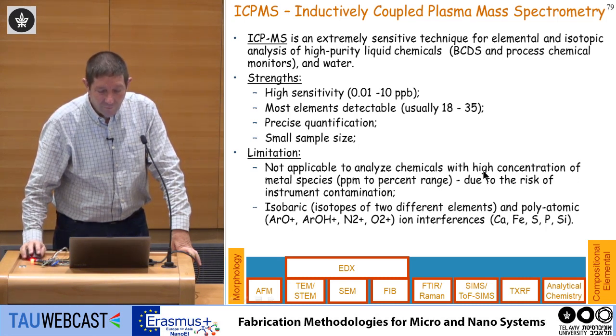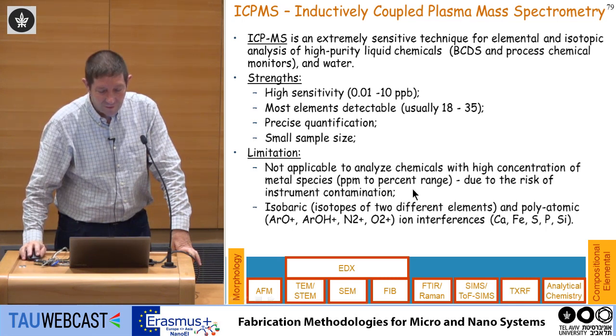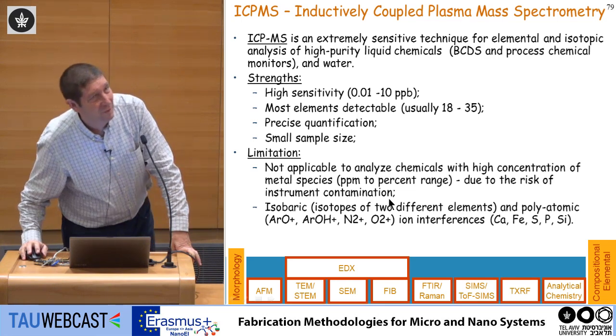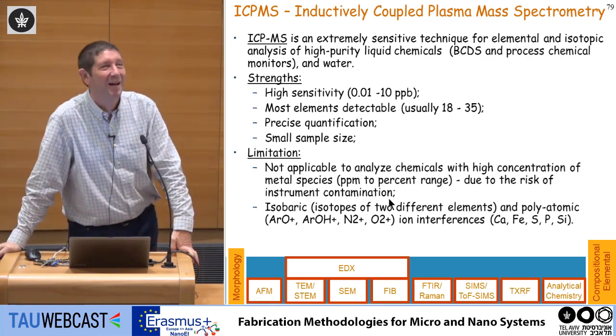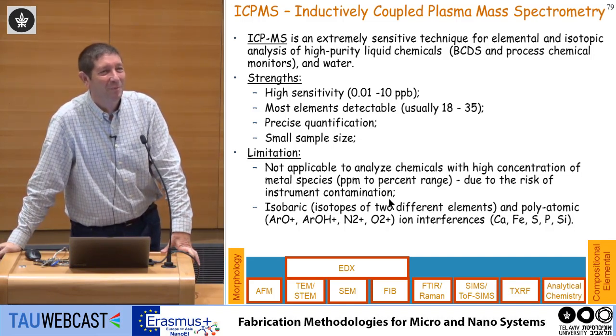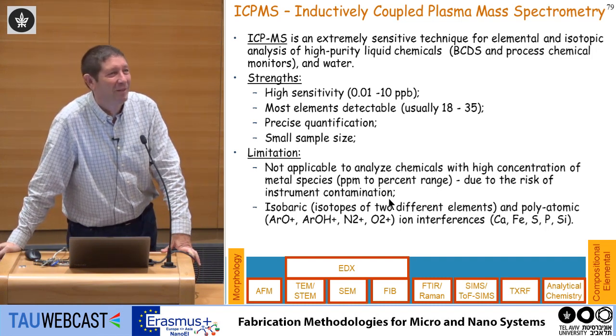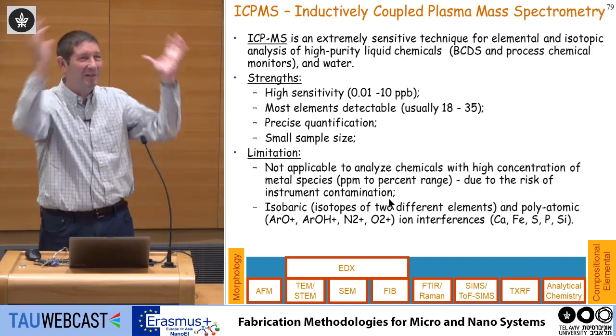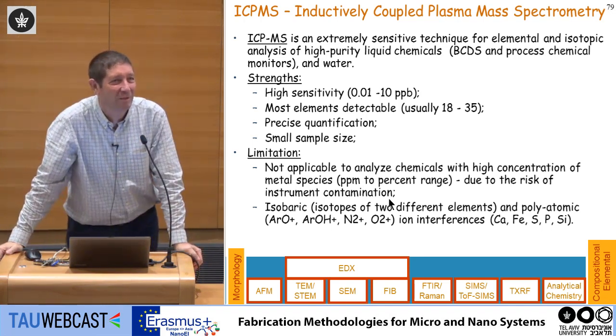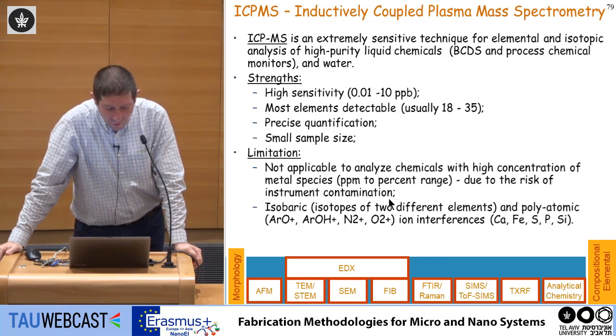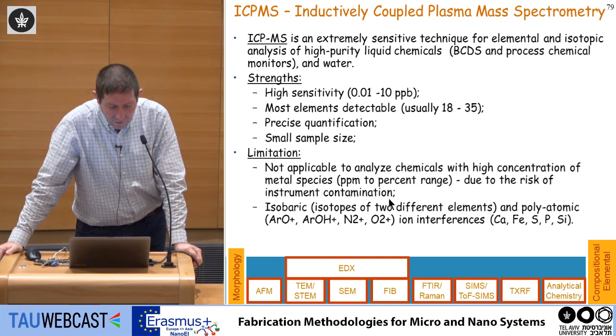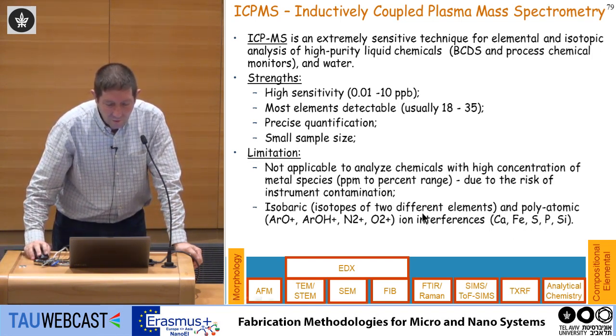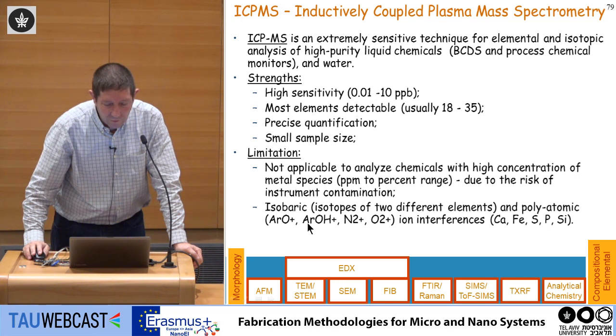But if you have a high concentration of metal species inside, it's not recommended because you can contaminate your system. Because this is a very, very sensitive method, what happens if you put something inside that contaminates the chamber? If you put metals inside, most likely some of the metal will stick to your chamber, and there goes a $500,000 system. So you have to be careful with metal contamination, and also with isobaric interference, isotopes of two different elements, and polyatomic ion interference. You can have interference between similar molecules, or molecules of two different elements.